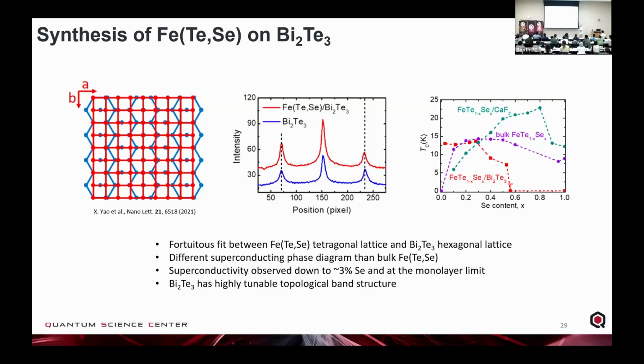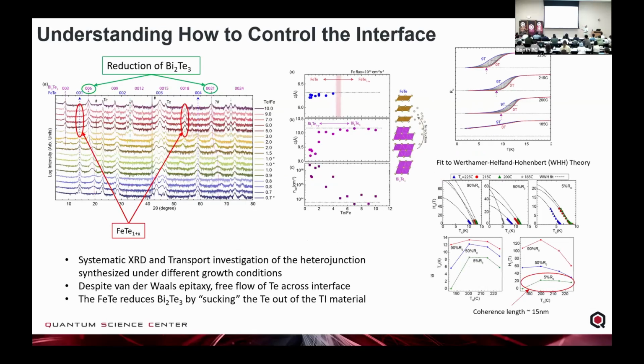Now, here's a situation where we're not really looking at the topology that is in the iron tellurium selenium, because we have the topology that is in the bismuth telluride itself. And so here, the iron tellurium selenium is just a superconductor. And then we have the bismuth telluride, which is a topological insulator. And so this is a candidate Fu-Kane model of topological superconductivity. The advantage here is that we can actually grow it with less and less selenium doping, so we can improve the homogeneity of the system itself.